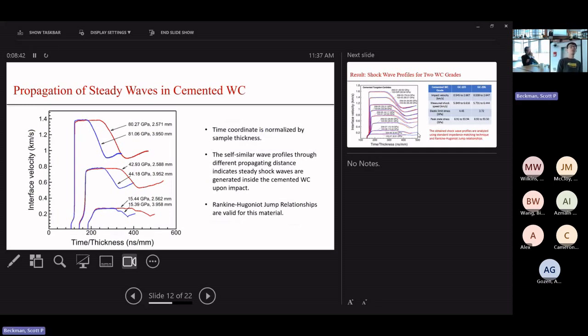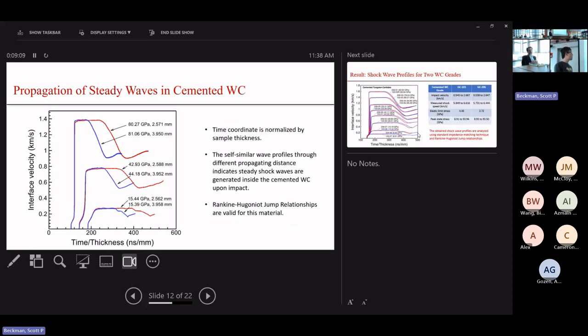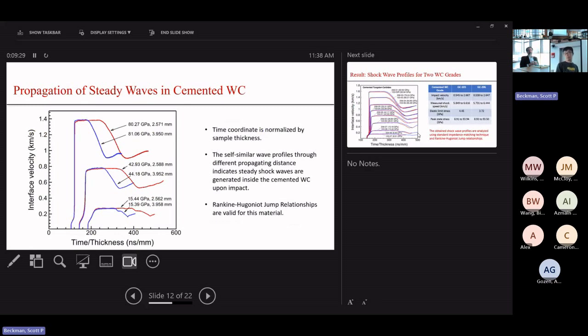We must ensure that for structured waves the shock speed is constant throughout the sample. We conducted experiments at different stress levels with different sample thicknesses, and the time coordinate is normalized by the sample thickness. As you can see, the shock profiles lie on top of each other, meaning the shock speed remains constant over different propagation distances. This confirms that the Rankine-Hugoniot jump relationships are valid for this material.